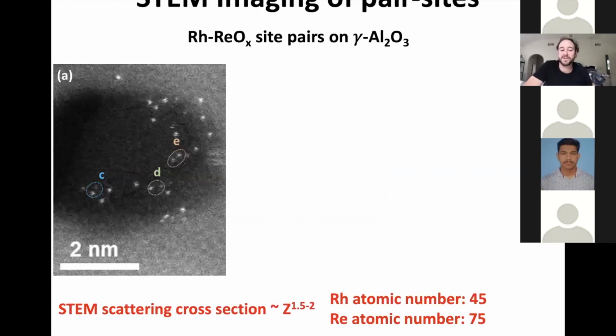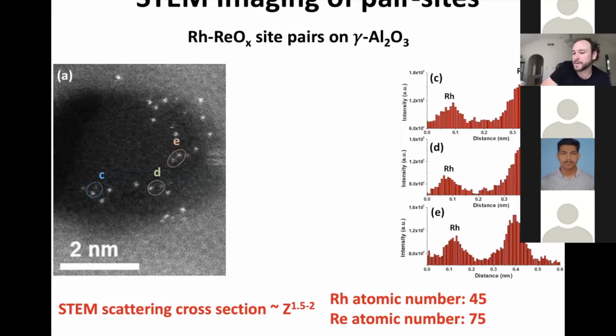So just to give you a taste of how we've been trying to do this, you can then go and make these materials, and you can use electron microscopy to say, have I made pairs of sites? So you can do aberration corrected electron microscopy. You can see bright spots, and this is 2 nanometers, so each one of these is a single atom. You can identify pairs, but how would I know if one is rhodium and one is rhenium? Well, rhodium has an atomic number of 45, rhenium has an atomic number of 75, and the scattering cross-section goes as about Z, the atomic number, to about 1.5 or 2. So we would expect a bright scatterer and a darker scatterer. And every time we identified pairs, we had higher scattering intensity, lower scattering intensity.